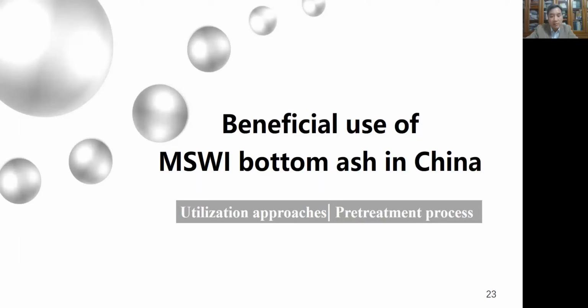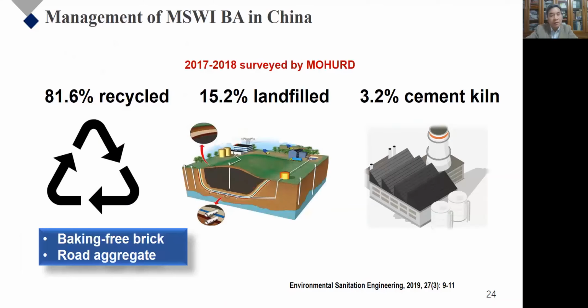Guided by the limited regulations and standards, beneficial use of bottom ash as construction materials has already been applied in different municipal solid waste incinerators in China, and pretreatment processes have been developed to recover valuable metals and remove unburned substances. According to a survey carried out by the Ministry of Housing and Urban Rural Development of China during 2017 to 2018, around 82% of bottom ash was recycled. 15% of bottom ash was landfilled, and 3% was co-processed in cement kilns. Most of the recycled bottom ash is used to produce baking-free bricks or aggregate for road engineering.